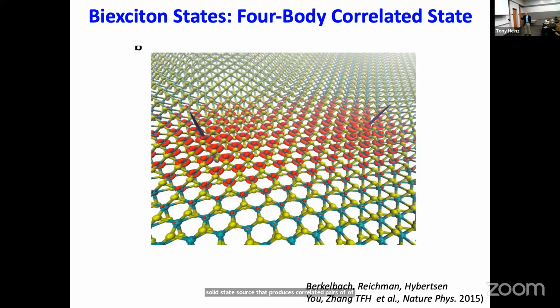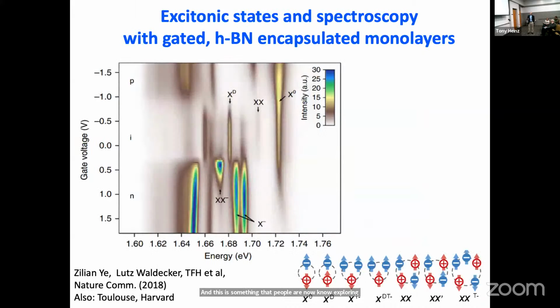So since you have two quanta of energy in a 2-photon decay, you're going to have correlation effects. And this is something that people are now exploring. The spectroscopy of these things has actually improved quite a bit by getting better samples, and we now know better how to protect them by encapsulating them in other van der Waals materials like this insulating boron nitride.